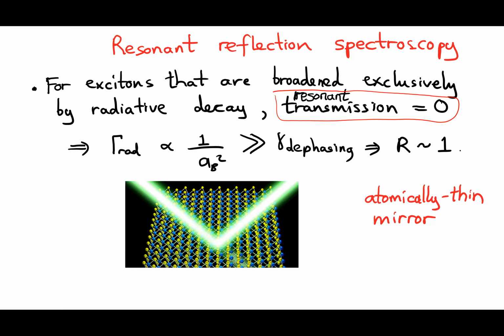An implication of that is that if you send light onto a material at the exciton resonance, then it will act as an atomic mirror. And what I mean by atomic mirror is that the reflection coefficient, the specular reflection, can be very high. So we see up to 70%. The highest value reported is 85%. So it's really interesting that one can realize such a linear optical effect. It's still linear optics, but it's interesting.